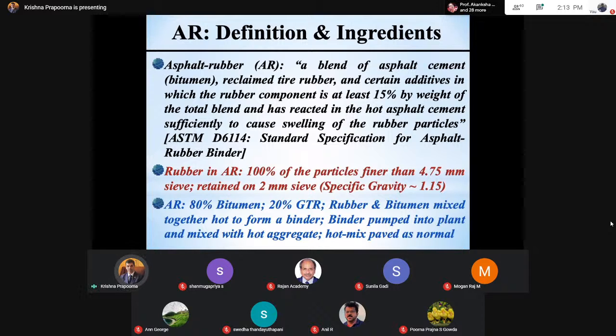Now, what is happening here? Is it a dearth of rubber particles? Not really. We have enough abundant tires being discarded in India too. So what is the problem then? There are problems associated with CRMB, and there are 2 major issues. One, storage. If you keep the rubber modified binder, I call it rubber modified, not AR as such, in India, because I told you it's not a 15% minimum, right? So we call it CRMB only, crumb rubber modified bitumen.